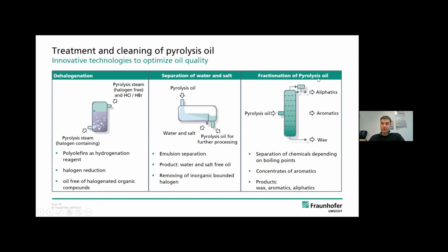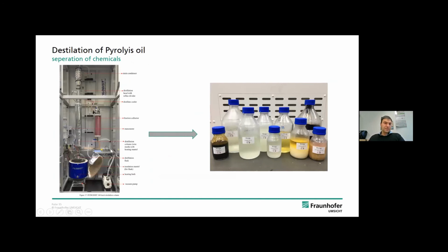After that, we go into distillation and fractionation of the pyrolysis oil, and we can get fractions like aliphatics, aromatics, or wax. So in our labs, this looks like that. We have a rectification column. And after the rectification of the pyrolysis oil, so here this black one, this is the pyrolysis oil, we end up with several fractions, which are made of benzene, toluene. We have a mixture of styrene and ethyl benzene. We have some phenol fractions, and we have a naphthalene fraction. And these fractions are pure, so more than 90% purity already.